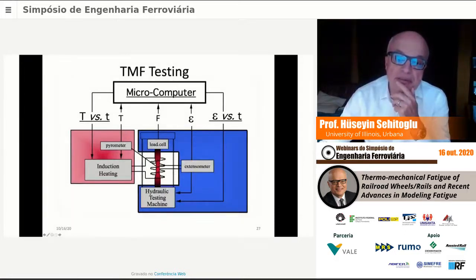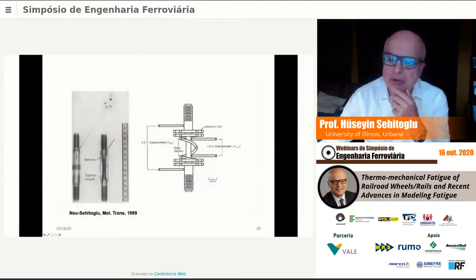Now, typically, the TMF testing, as I mentioned, you have a load cell, you have a hydraulic test machine. You need to measure the temperature. We used to use thermocouples. Now we're using pyrometers. And we have an induction heater. Both of them are controlled. The temperature is controlled. And the strain is measured also with an extensometer. And they are fed into a computer so that we could control the experiments.